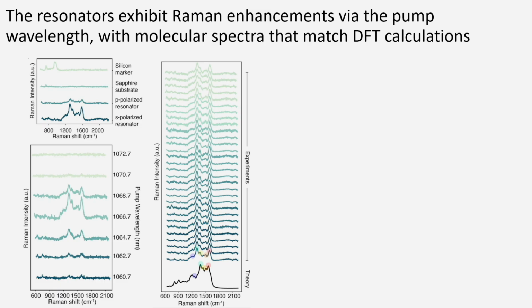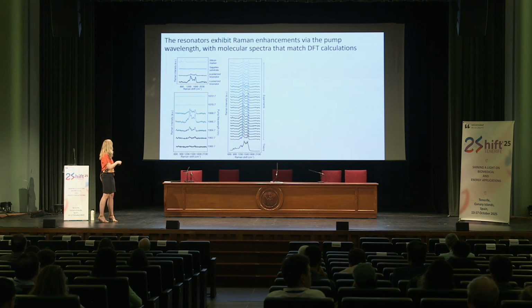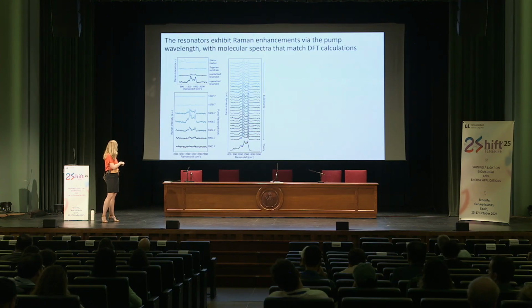And here I just want to share with you that when we have the right polarization of light, you can see the Raman intensity of this particular molecule is quite strong compared to when we have the wrong polarization of light. And similarly, when we are on resonance, at that high quality factor resonance, that boosts the quality factor and the mode volume at the pump wavelength, you can also see that the Raman scattering goes up quite substantially, whereas if you're just off that high Q resonance, you don't get any Raman scattering signal. And then what we can do is collect Raman spectra from many of our resonators.